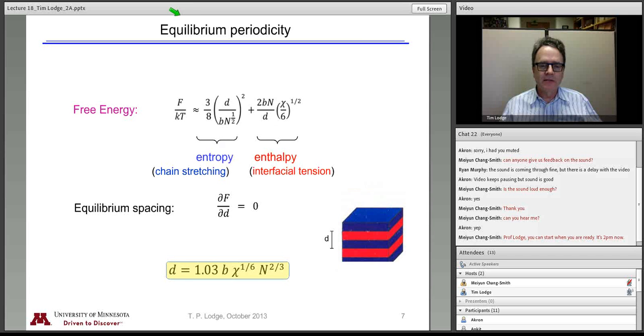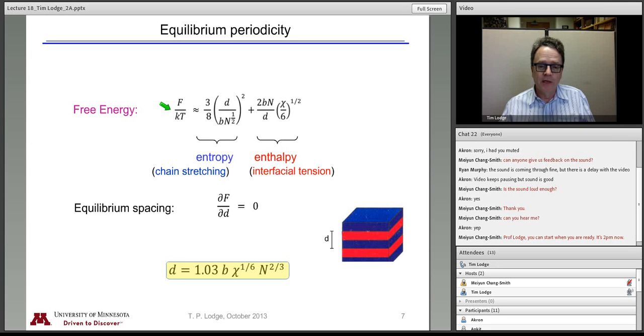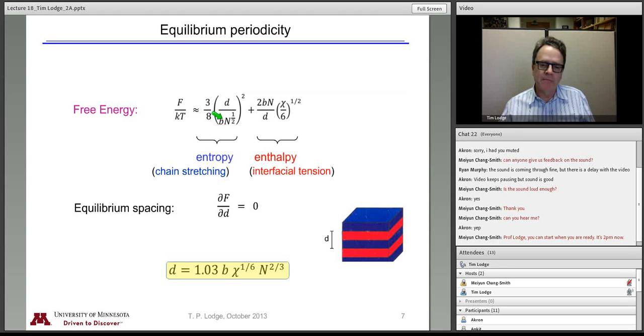The complete analysis takes those two concepts — entropy of the blocks and enthalpy due to the interface — and constructs a free energy expression with these two contributions. The stretching goes as the square of the period divided by the unperturbed end-to-end distance B√N — this is the entropic elasticity of a single Gaussian chain, the same thing that appears in the theory of rubber elasticity. This term accounts for the interface, which is proportional to √χ, the interaction parameter. It depends on N and D because of how much interface you have per chain.